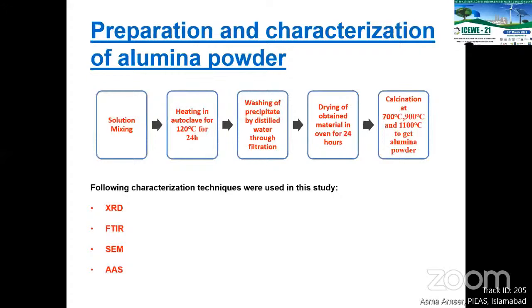Next is the preparation and characterization of alumina powders. In this process, first of all, an aqueous solution of urea and an aqueous solution of aluminum nitrate were mixed by stirring. Then this mixture was transferred into an autoclave and heated for 24 hours at 120 degrees C. After 24 hours it was taken out and washing was done by filtration.